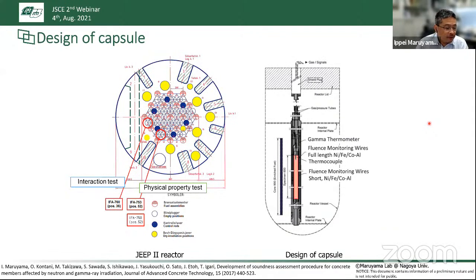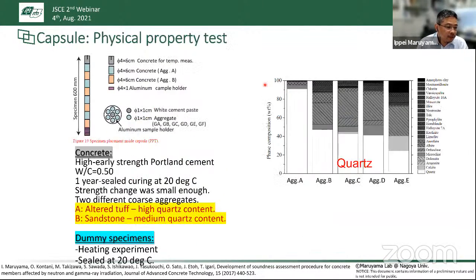And this is the view of the inside of the reactor. And this is the schematic figure of the design of the capsule, which stores the specimens during the neutron irradiation. In the capsule, for the irradiation experiment, we set 4 different neutron irradiation levels, and 2 different concrete specimens are prepared. The water to cement ratio is common, about 0.5, and only the type of the coarse aggregate is changed. One is the Altered tuff, which has a large amount of quartz inside, and the other is a general ordinary sandstone, whose alpha quartz content is about 50%.